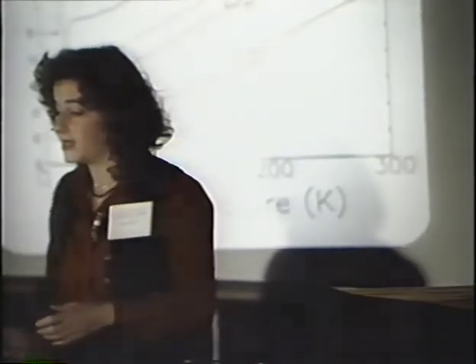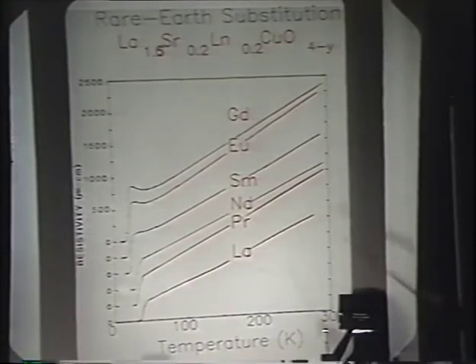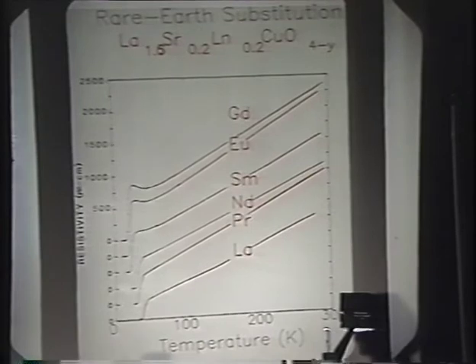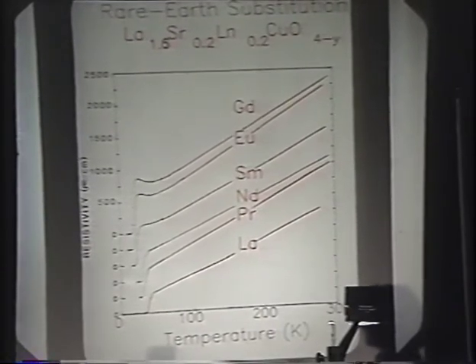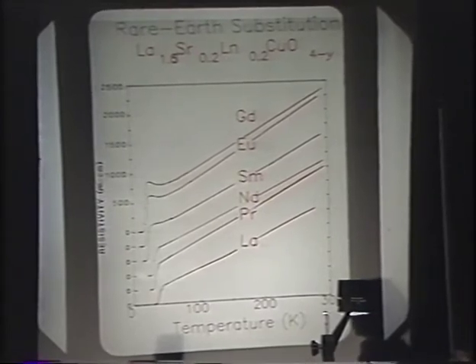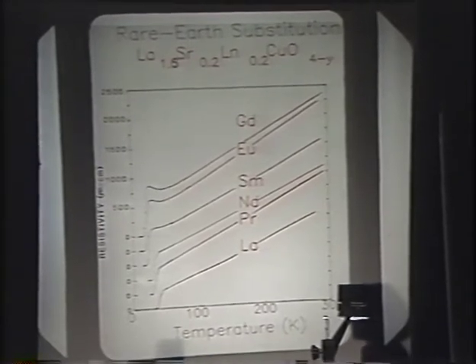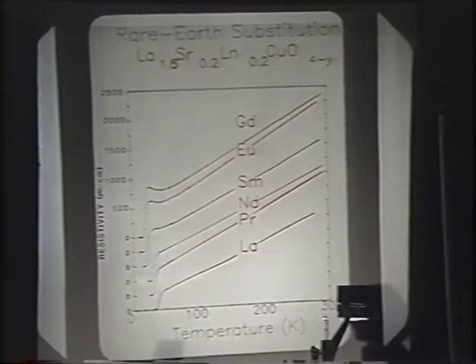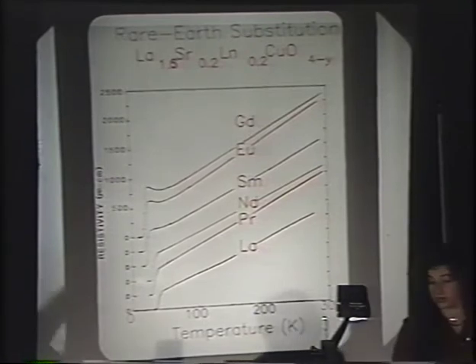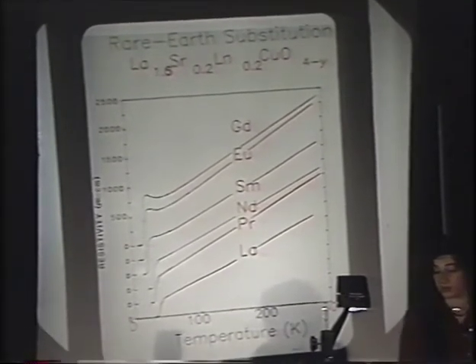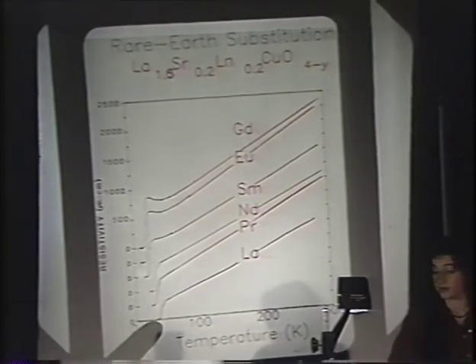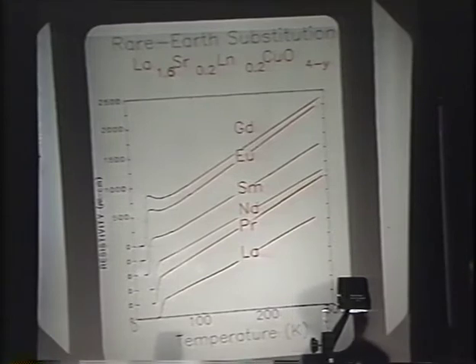This is in contrast to our rare earth substitution work in the lanthanum strontium copper oxides. Here we've doped with the lanthanides and rare earths, as shown here. Note these also have surprisingly linear resistivities throughout the temperature range up to room temperature. In these with the rare earth dopings, we find the room temperature resistivities are all comparable, and the slopes of all these materials in resistivity are all about the same. The main difference here is that the Tcs are pushed down as one dopes along the rare earth row, from 36.8 midpoint down to 18.5 for the gadolinium midpoint. We believe that this reduction in Tc is not due to a magnetic doping effect, but is due to volume change with the doping.